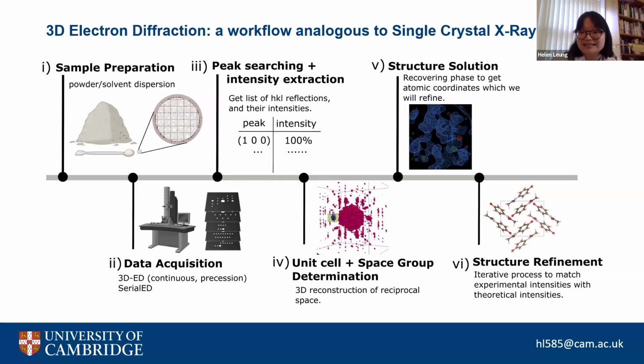There are many different ways that you could acquire that data. For example, you can precess the beam, or you can have a serial approach. But the goal is to collect your tilt series, which fairly represents all of reciprocal space, or as much as possible of it. From there, you can do your peak searching, intensity extraction, and understand what the unit cell and the space group of your compound is. And from there, work to recover the phase via structure solution and then a structure refinement.